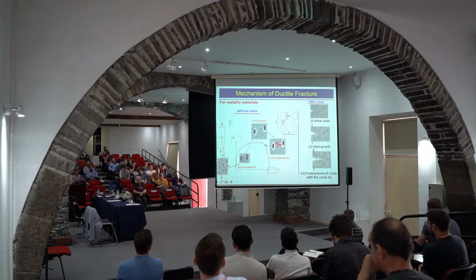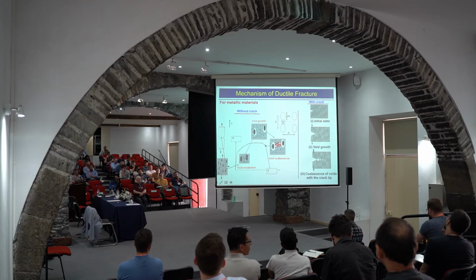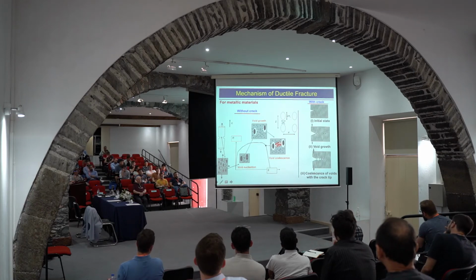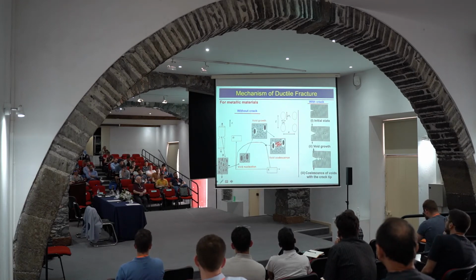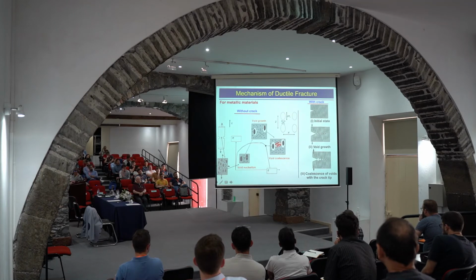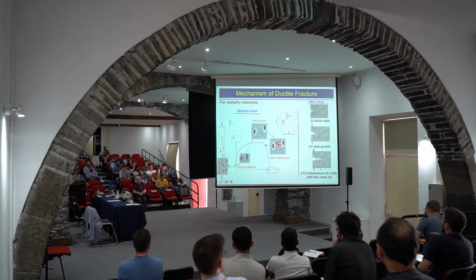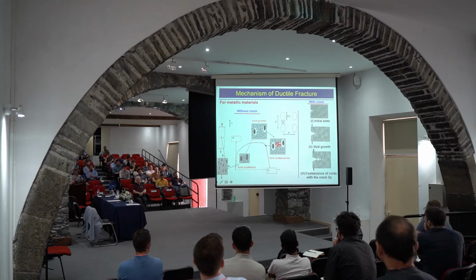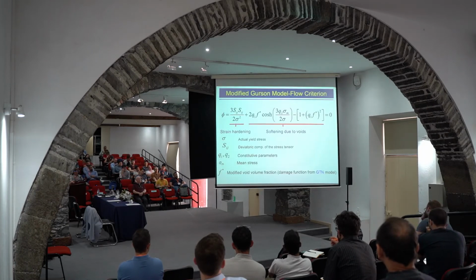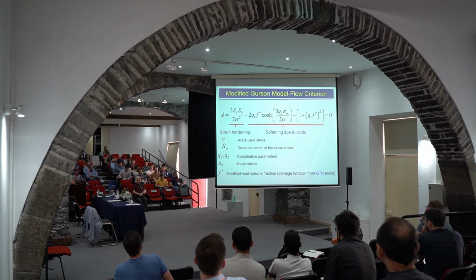And around this inclusion, voids start to nucleate, and then they grow, and then they coalesce at some critical event, and this is how stable crack growth can be described. You can see it also here. If there is already a crack, you can see some inclusions here, then voids, and then their growth and their coalescence. And that can be described in the scope of continuum mechanics by the so-called Gurson model and its modifications.